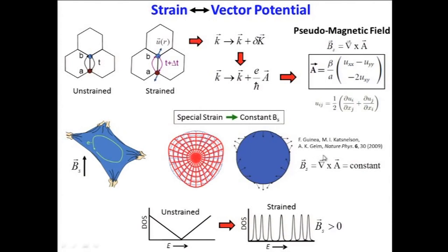And so this is a really nice paper where they came up with this clever idea of taking this mapping, and they figured out a particular strain geometry in which the resulting pseudo-magnetic field would be constant, which would cause the electrons to go around in a circle, leading to Landau levels, pseudo-Landau levels. What they figured out is that if you create a trigonal strain pattern, one that has triangular symmetry, then if you work through the details of this formula, that should lead to a constant magnetic field. The question, of course, is how to test this idea.